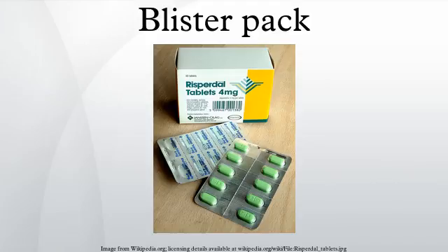Polychlorotrifluoroethylene (PCTFE) can be laminated to PVC to obtain very high moisture barrier. Typical constructions used for pharmaceutical products are 250-micron PVC film laminated to 15–150 micron PCTFE film. Duplex structures are PVC-PCTFE and triplex laminates are PVC-PE-PCTFE. Deeper cavities can be formed by using the triplex structures with PE. Typical water vapor transmission rate values are 0.06–0.40 g/m²/day.